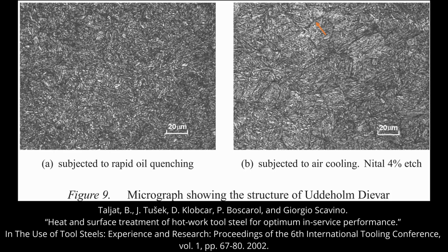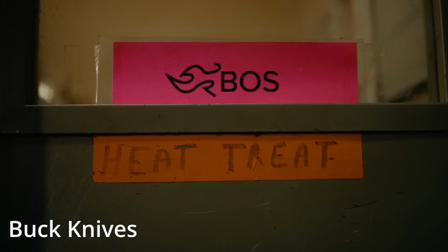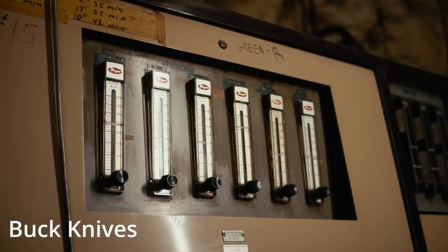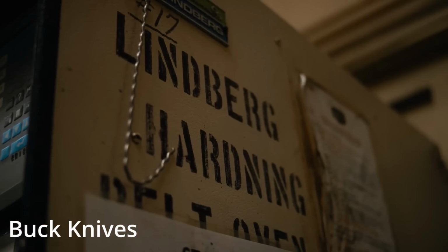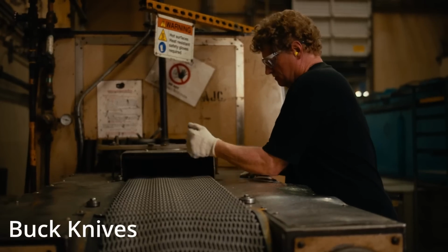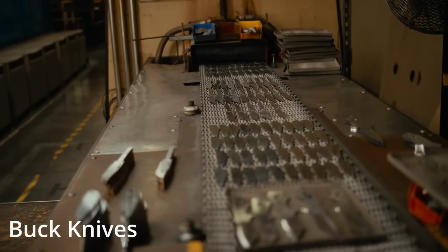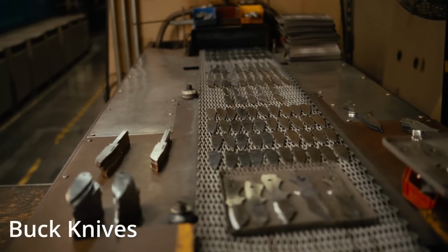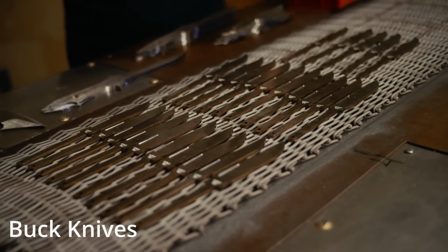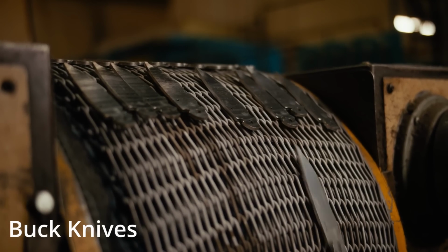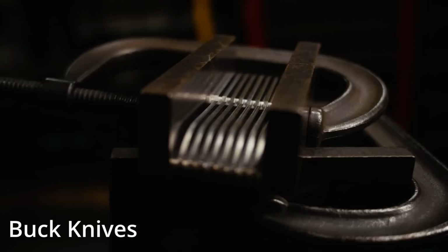So vacuum furnaces are not the only method used by production knife facilities, but they are by far the most common. One counterexample would be Paul Bos Heat Treating, which is located at Buck Knives, and they also perform all of the heat treating for Buck. So they use a conveyor belt furnace, and the steel comes out the other side and cools in air. This type of cooling is generally faster than a pressure quench in a vacuum furnace because of how much time it takes to cool down a fully loaded vacuum furnace, as opposed to these individual blades coming out and cooling in air on the conveyor belt.